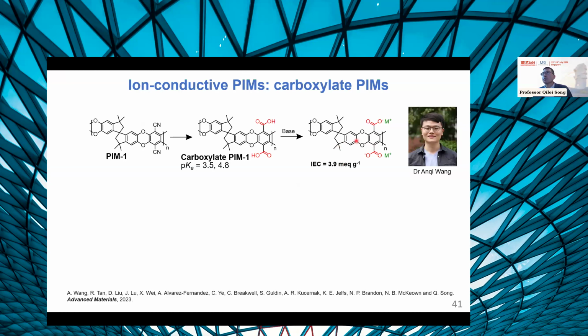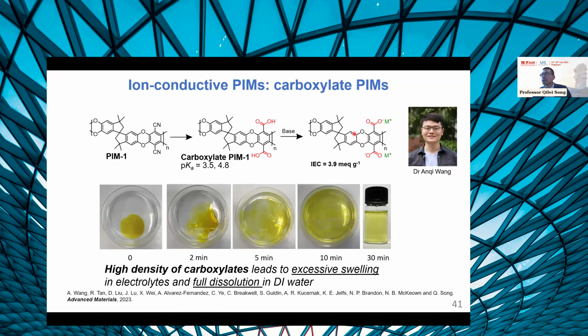For example, the carboxylate functional group that has relatively lower pKa, so the ion dissociation can be achieved in a neutral pH electrolyte. So this is the work we did. We converted the PIM1 to carboxylate PIMs. And unfortunately, because these carboxylate groups absorb a lot of water molecules, you can see that they show significant swelling and become fully dissolved in water. So this was not good for the membrane development because the membrane swells too much.